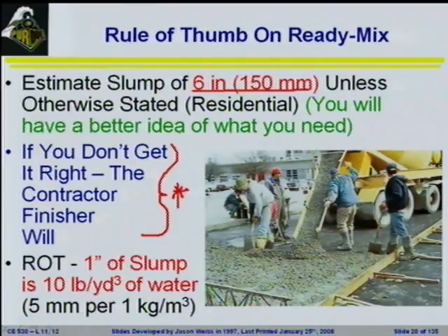The reason that contractors do that is because they want the workers to be happy. What is not understood many times is the rule of thumb comes with a decrease in strength, an increase in permeability, and a decrease in durability. So what we want to try to do at this stage is make the potential for the contractor to want to add water very, very low, and we want to design from a high slump right from the start. We want to design something that people can place without having to add water, so there isn't a huge fight when it gets out on the construction site.